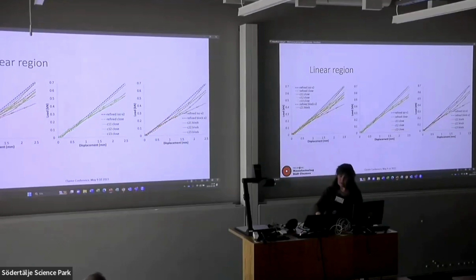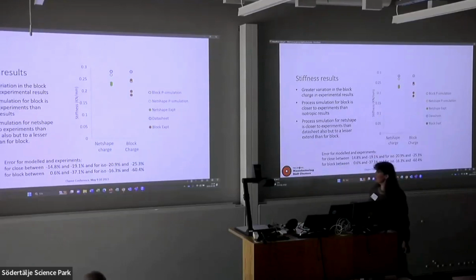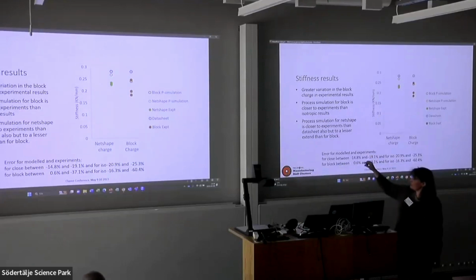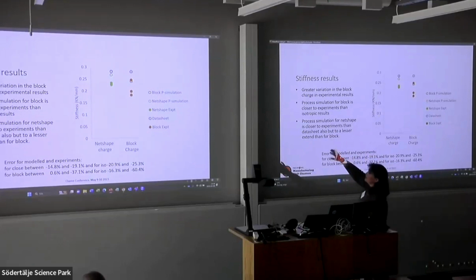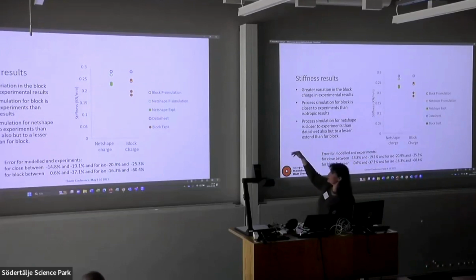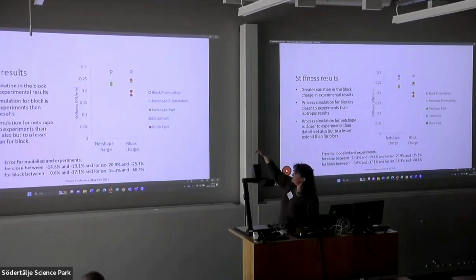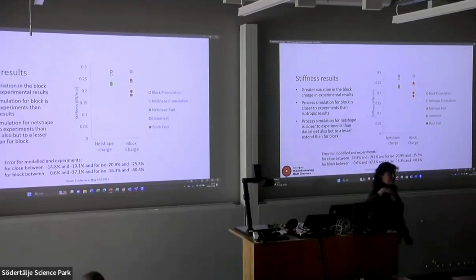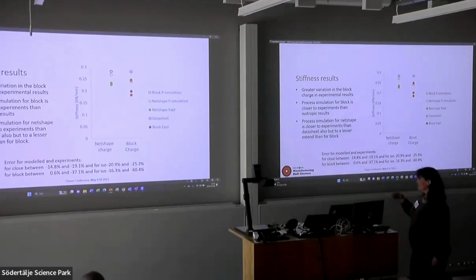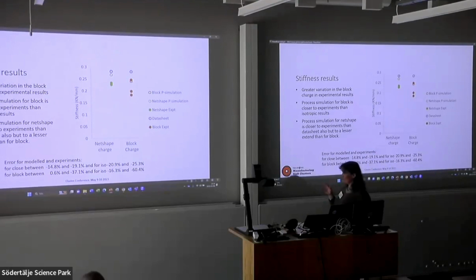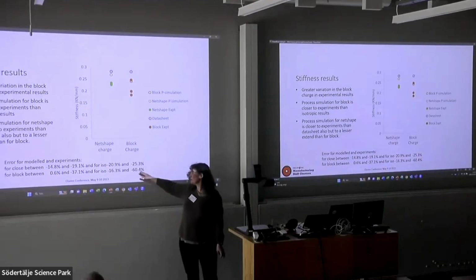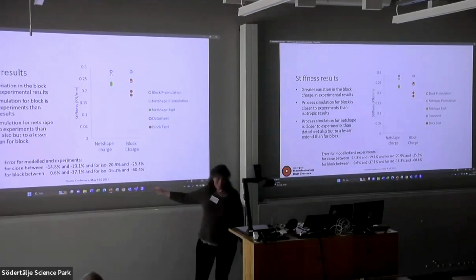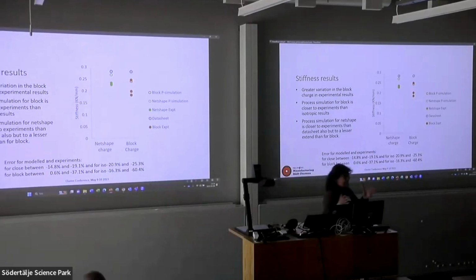If we look again a little bit more at the stiffness, we can see that the variation was less with the net shape than it was with the block, and that the prediction using the process simulation was a bit closer in both cases, but of course it makes much less difference to a net shape than it does to a block. I was looking at some of these tolerances. This is worst case with only 1 degree. This is 60% wrong. So we really need to get this variation down.